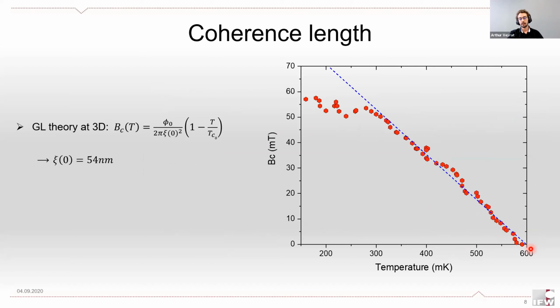So as you can see, the critical field behaves very linearly with temperature down to temperatures quite far away from the critical temperature. This is expected from the Ginzburg-Landau theory in 3 dimensions, from which we can extract a zero temperature value of the superconducting coherence length of about 54 nanometers. This is quite interesting because, as I said before, trigonal platinum bismuth 2 is a van der Waals material, so it is possible to exfoliate it mechanically using Scotch tape down to such thicknesses. And this way, we may be able to study the behavior of superconductivity when it is constricted to 2 dimensions.